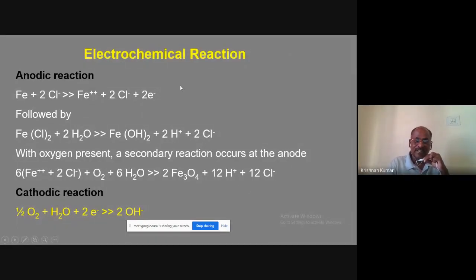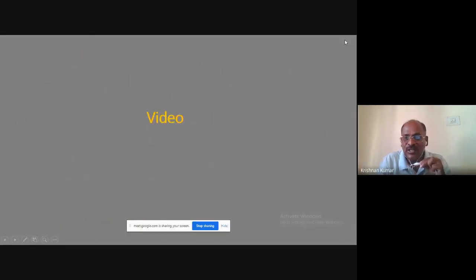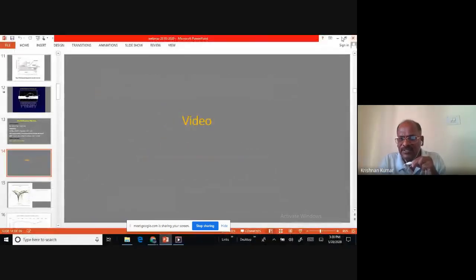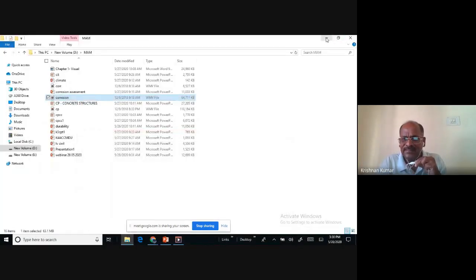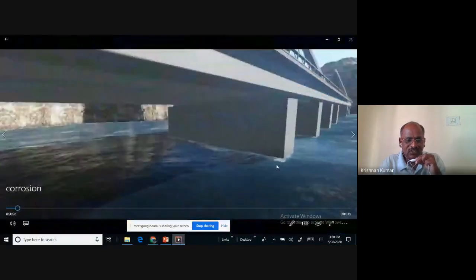So this is the cathode reaction, where the 2e- is consumed, and the cathodic reaction is coming. Here what we can observe is that chloride is the major part which not only initiates but also propagates the corrosion. We have to avoid chloride reaching the steel surface to protect our structure. That is the conclusion we can have here in the electrochemical reaction. Now I wanted to give you a small video. You can just see one video here. I think that is quite good. You will have an idea.